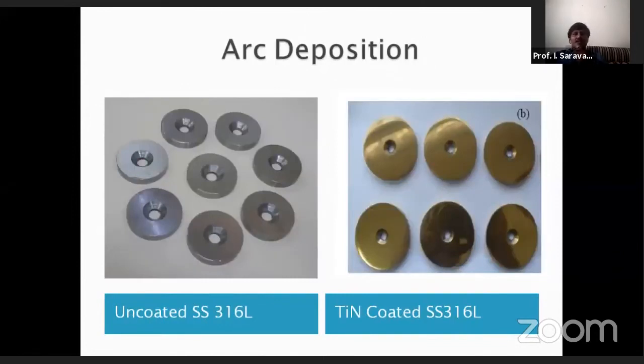And this is from our research work. We have chosen titanium nitride coated stainless steel against polymer composites of ultra high molecular weight polyethylene. After the wear test, on the worn surface we can find the morphological changes, debris and ploughing, and the polymer composite having some flashes. These are the surface defects at the time of the wear test. The input parameters for the wear test are 2 Newton, 4 Newton, and 6 Newton, and the corresponding sliding speeds are 0.25, 0.5, and 0.75 meter per second, and the distances are 500, 1000, and 1500 meters.